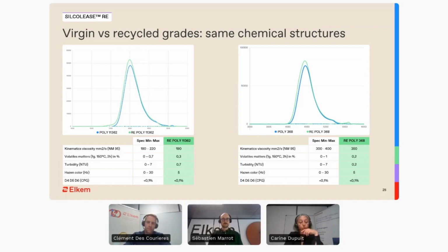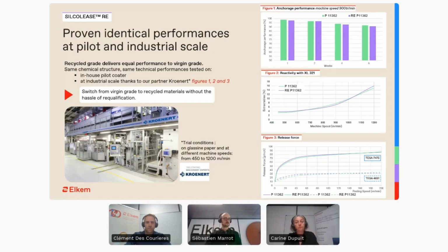All the results also proved the strict equivalence of the recycled grade with the virgin counterparts from a chemical and polymeric structure point of view. Processability and release performances of both SILCOLEASE recycled grades have first been checked on Elkem's pilot coater, the same one that Sebastian mentioned previously.